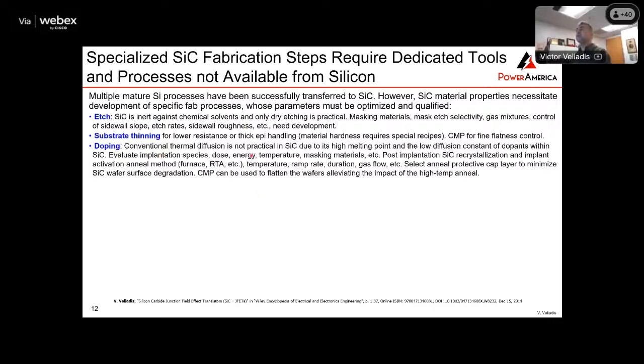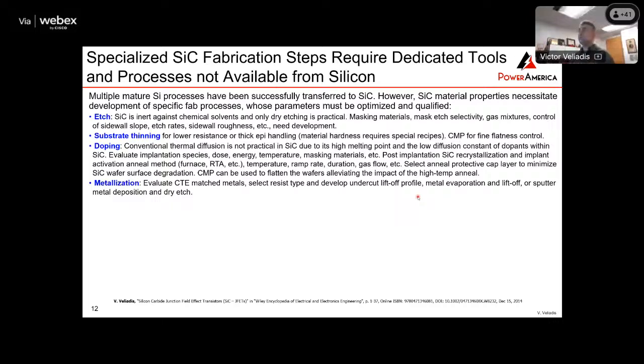When it comes to doping, thermal diffusion is not practical in silicon carbide. You have to go to temperatures that are in the 3000 degrees or so, because of the very high melting point of silicon carbide, the low diffusion constant. So doping is done by implantation. You implant a species into silicon carbide, and you have to adjust the dose, the energy, the temperature, the right materials. And then after you're done with implantation, you have to do a post-implantation anneal to basically activate the dopants and recrystallize the wafer. When it comes to metallization, we all know that you've got to have materials with a coefficient of thermal expansion that's matched. So therefore, the metals that you use for silicon carbide have to match the CTE of silicon carbide.